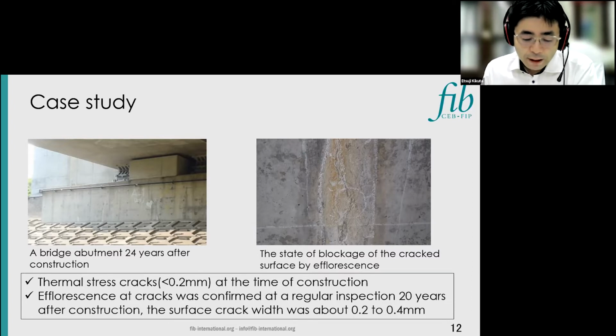Then, efflorescence deposition from the cracks was confirmed in the inspection 20 years after construction, and the surface crack width had expanded slightly to about 0.2 to 0.4 millimeters. Therefore, a detailed investigation was carried out and repair interventions were considered.